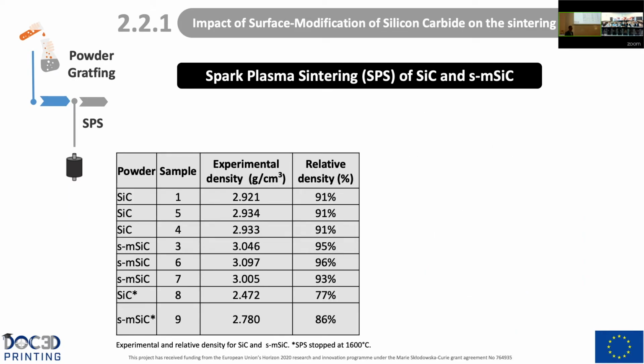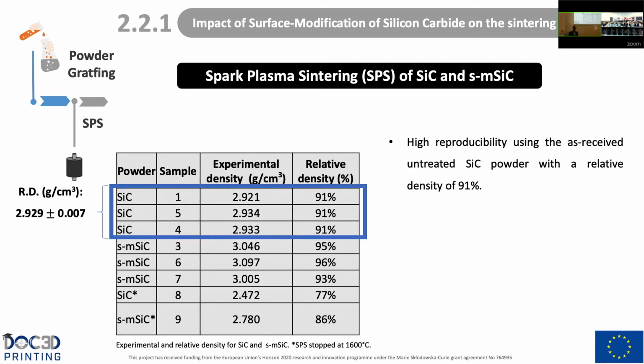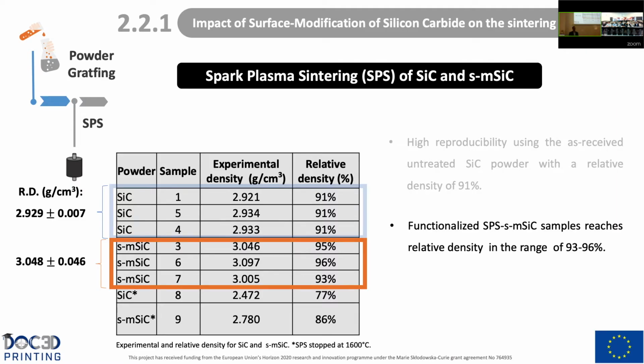Now, regarding the relative density of the silicon carbide versus the surface modified silicon carbide, here we observe a high reproducibility using the powder as received, with a relative density of 91%. On the other hand, using the functionalized surface modified silicon carbide, the samples reach a relative density in the range of 93 and 96%, very close to full densification. So we are increasing on average 4% the relative density by using surface modified silicon carbide.